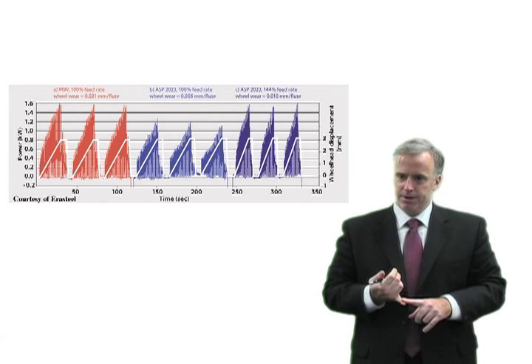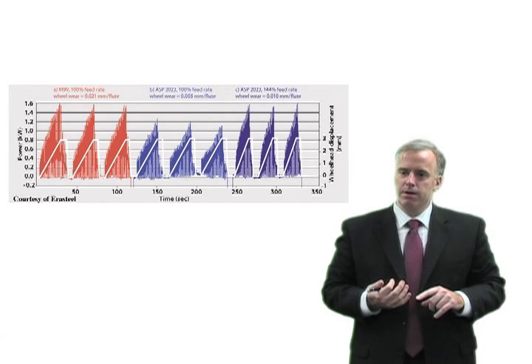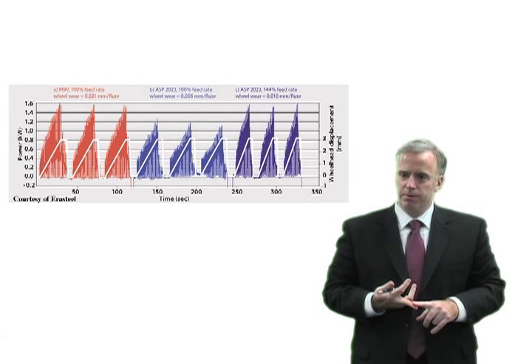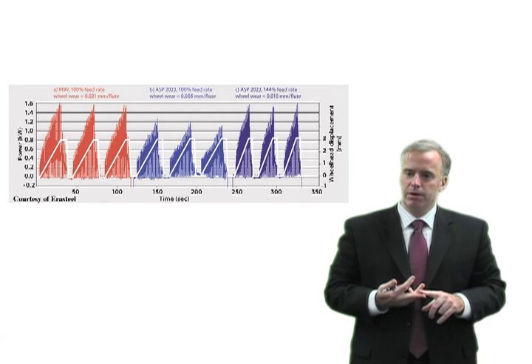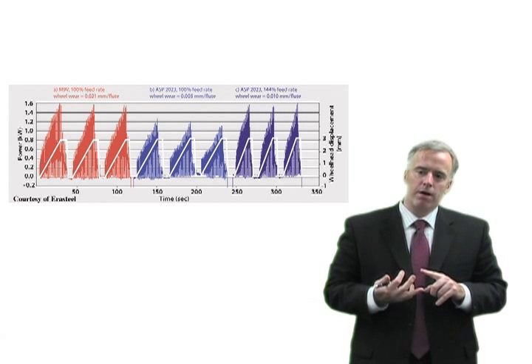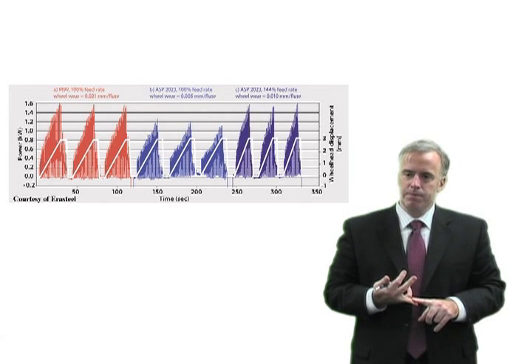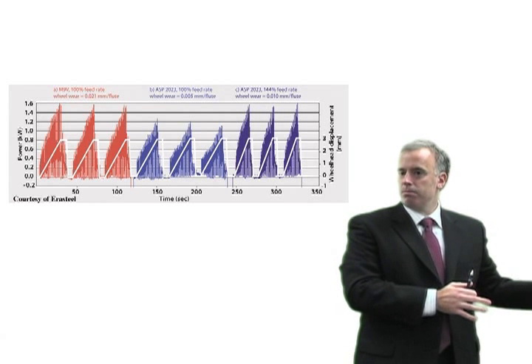Within a family of materials, say high-speed steel, some grades are just more difficult to grind than others. That's the way it is. It has to do with the amount of tungsten, vanadium, molybdenum, cobalt, how you harden it, everything else. But some are just a lot more difficult to grind.